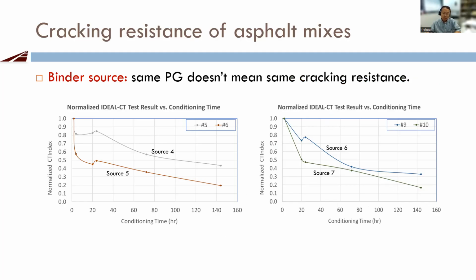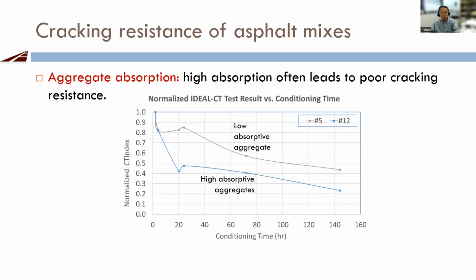You can see the age is completely different. Same thing for another two mixes. This is PG 64-28. This is 64-22. And not just the binder source, aggregate absorption has another significant impact on cracking resistance.